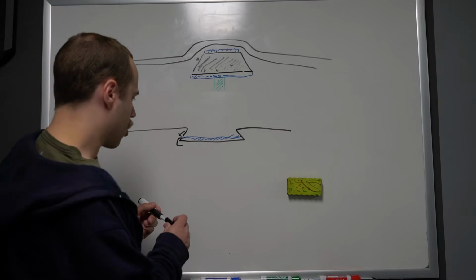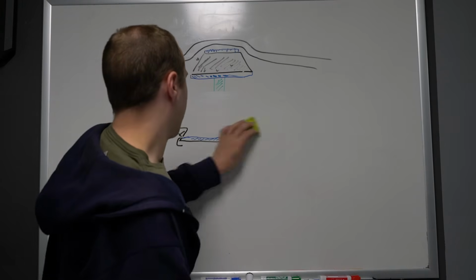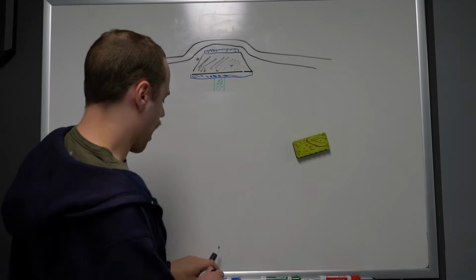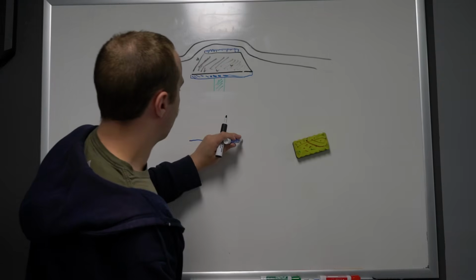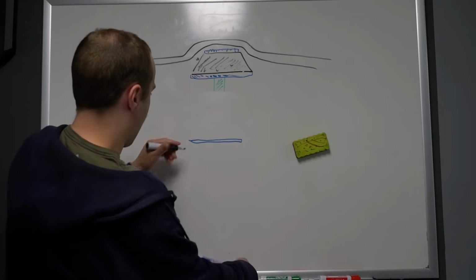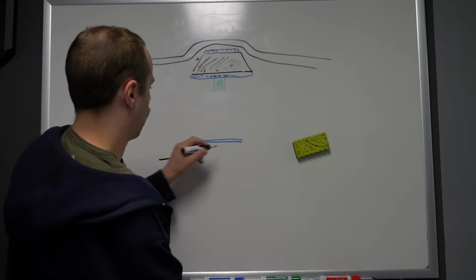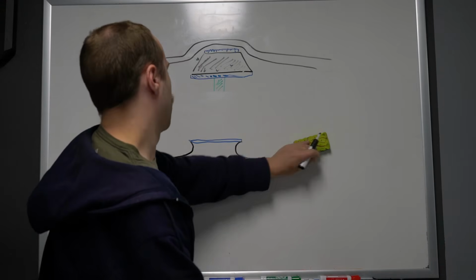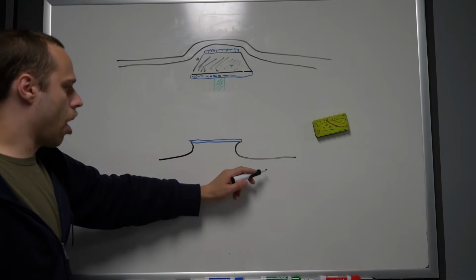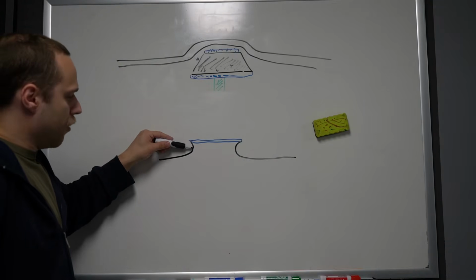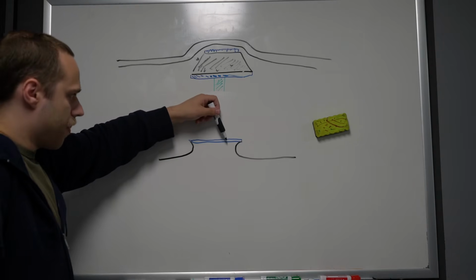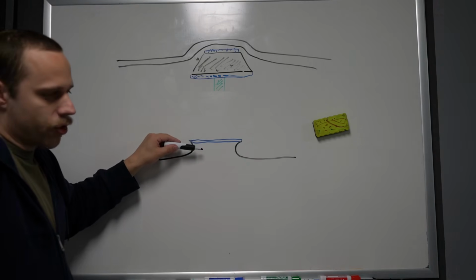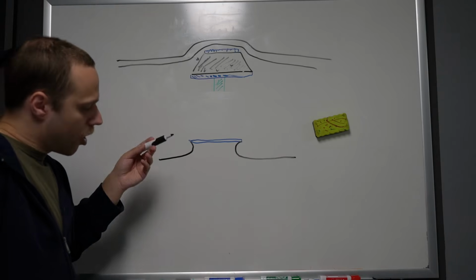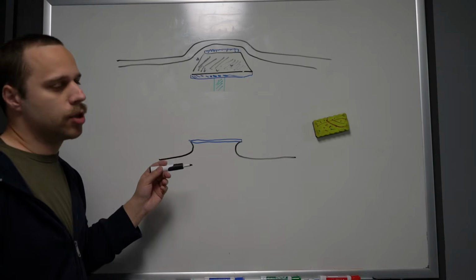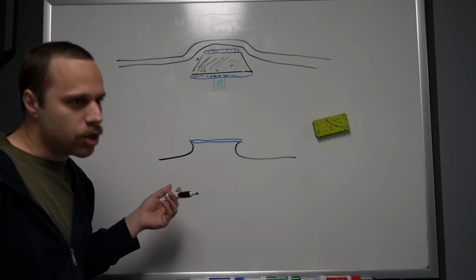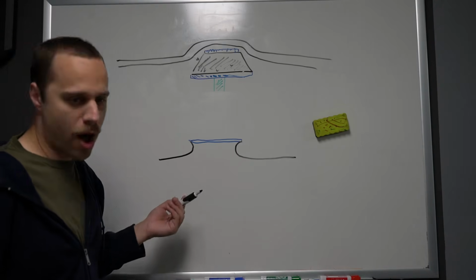because what we don't want to do is create a pedestal where we've etched down a bunch more and we have this titanium nitride layer here, and now we've got something like this where we have our glass layer below it, and the HF is slowly eating in from the edges and is not doing a whole lot to the top, and we end up having this hump of dielectric, which is going to cause shadowing of lower layers. And again, some of these effects are impossible to eliminate. This is the reason why wet etching is not used in serious deprocessing, especially on more modern nodes.